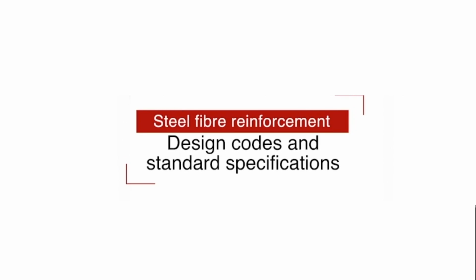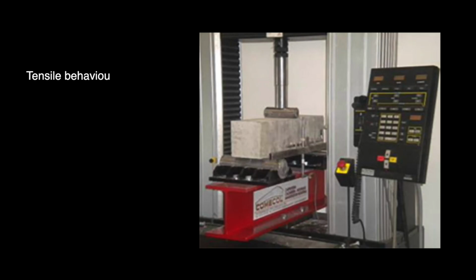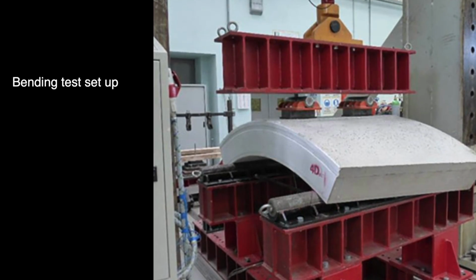Nowadays, most of the specifications mention quality. It's the same as in concrete. In the past, in the specification, we had a mix design, 300 kilos of cement per cubic meter. Nowadays, they specify a compressive strength. For fibrous concrete, now mostly they specify bending moment strength, because in fact you add steel to the concrete to improve the bending strength, to improve tensile strength. So, when you already have the right specification for your material, it becomes much easier to design it also.